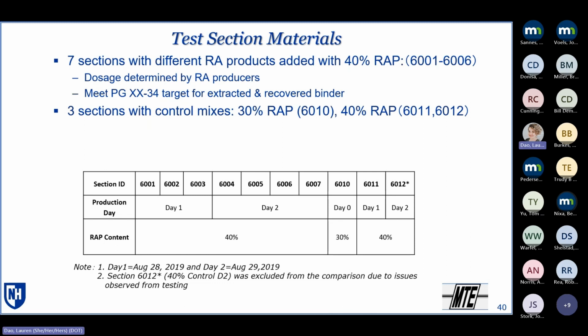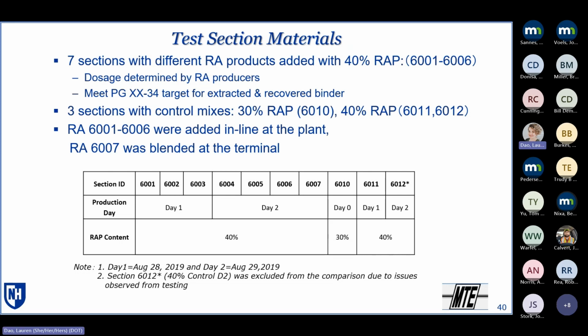Now, one thing to note when I'm showing the results: as we were getting into the project and getting some of the results, the results for the second day 40% control mixtures just weren't making sense. Something was not right with the material that we had. All of that data is shown in the reports, but what I'm showing today, we've dropped out of the direct comparison. We looked into some of the production, trying to get some of the plant information, but couldn't figure out what had happened with these materials, but obviously it wasn't a good comparator. So we're sticking with just the day 1 materials. You'll notice that those aren't on there, but they are shown in the reports that are online. And one other thing to note, 6 of the products were added inline, and one of them was a terminal blended material.